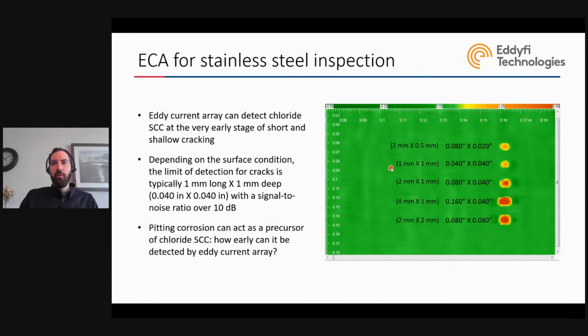So this was another trial here with just artificial defects on a perfect surface condition, stainless steel 316. In this case, like I said, we were able to find 1 millimeter crack. So this is a very high resolution probe that allowed to find very small indications, very small flaws.